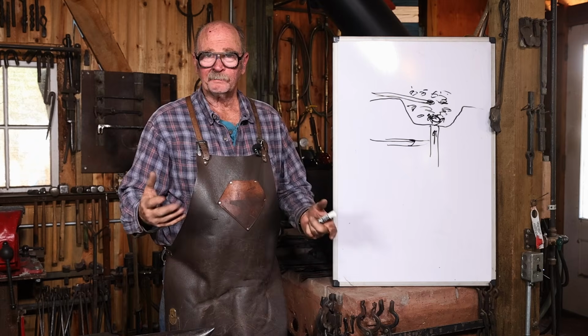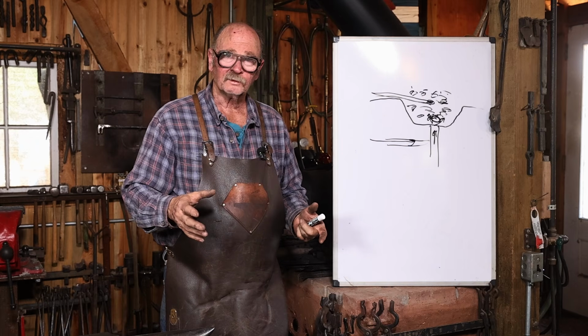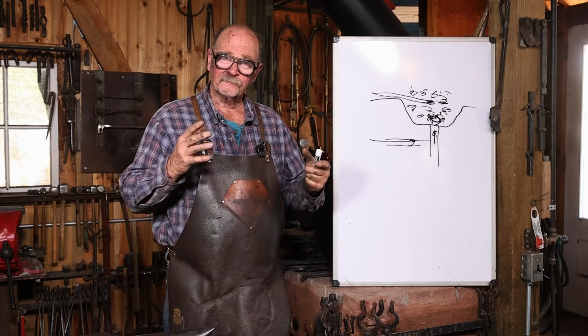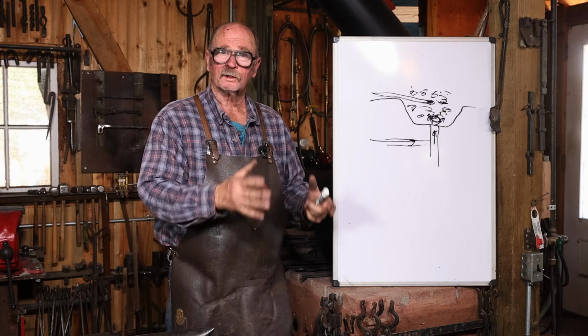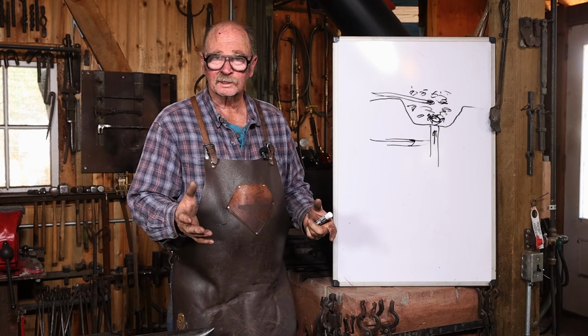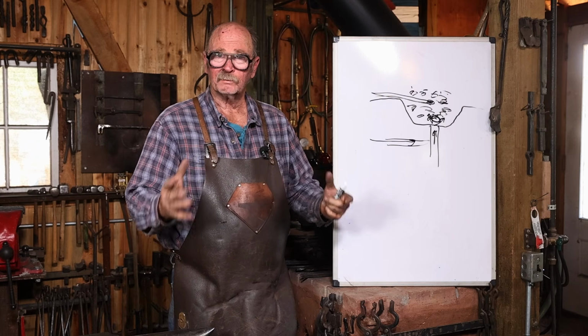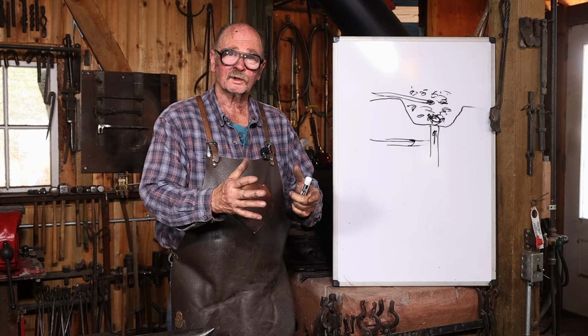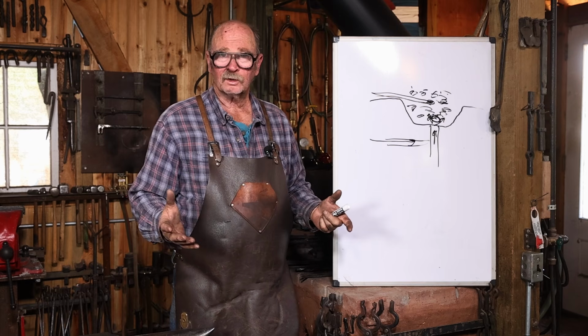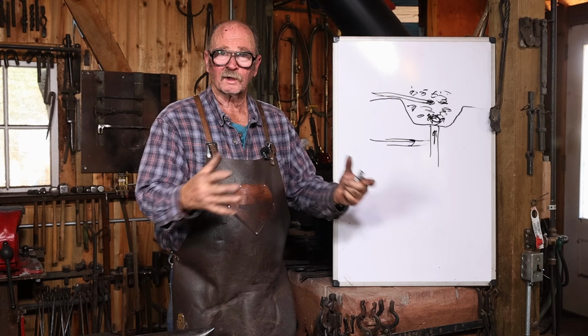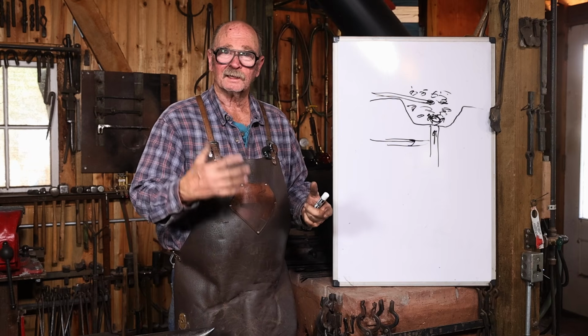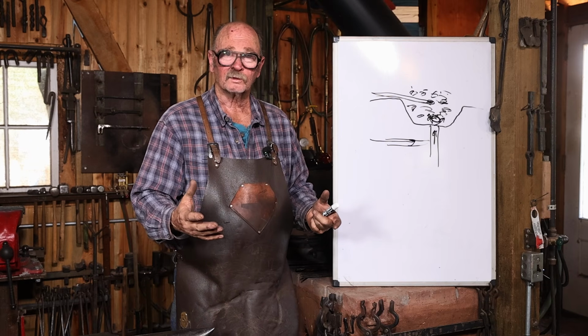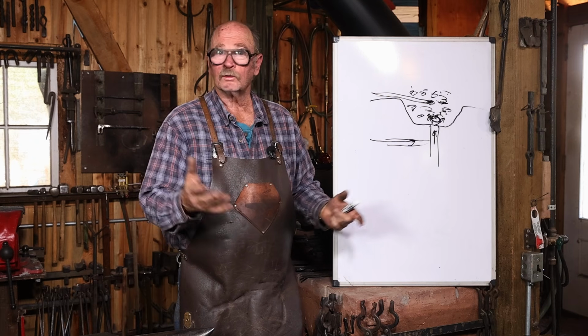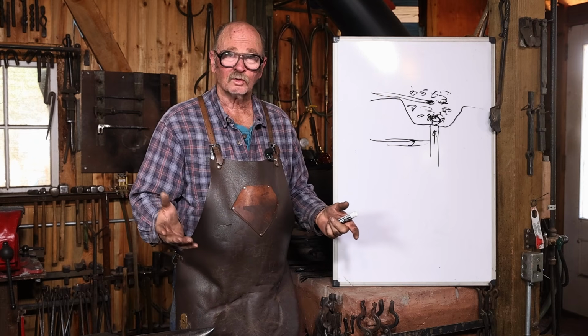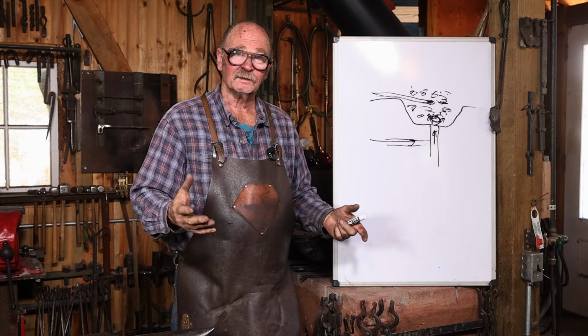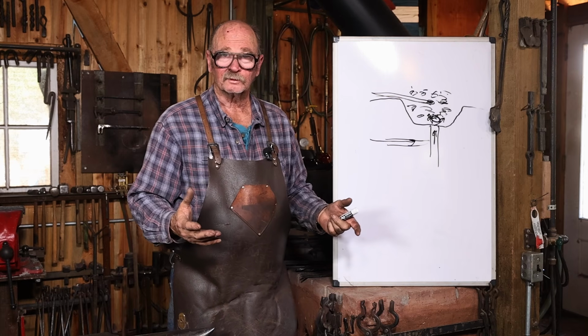Now, besides having a high BTU fuel, good clean fuel, you don't want to be putting fresh green coal on the fire while you're forge welding. That just robs heat energy. You want your coal to be coking and be putting coke on the fire while you're working. Or if you're using commercially made coke, you can just put commercial coke on the fire while you're working and keep bringing that in so you've got good fresh fuel for forge welding. Same thing applies to charcoal. You can forge weld just fine in charcoal, but you're going to need a lot of it because it eats it up really fast at those high heats.